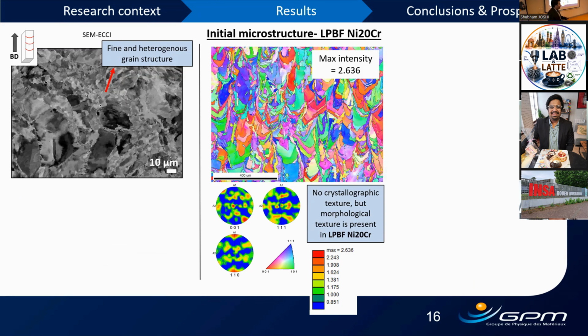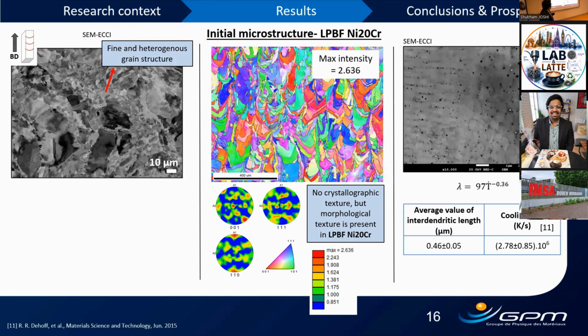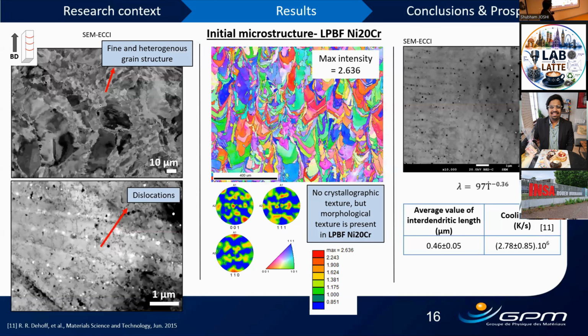which means that this parameter set does not induce a lot of crystallographic texture, but we can clearly see some morphological texture. Talking about another aspect of microstructure, when we magnify, we see these different colonies of dendrites or dendritic cellular structures, and there are several names which will be used in the presentation, but they are the same thing. These two colonies can be seen with an average cell size computed to be 0.46 microns.